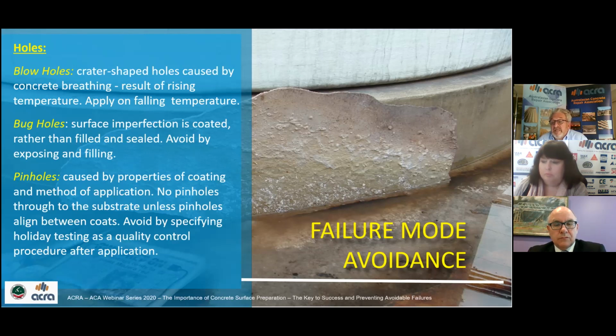Bug holes are surface imperfections in the concrete that have attempted to be coated. Common defects are that some concrete's never coated. The hole is covered with a thin skin of concrete, which eventually fractures since it's not structurally sound. In either case, the concrete's exposed, thus defeating the purpose of the coating. It can be avoided by insisting all bug holes are exposed by opening them up and filled with material compatible with the coating system.